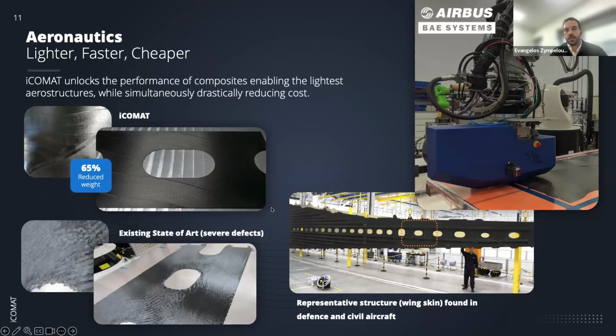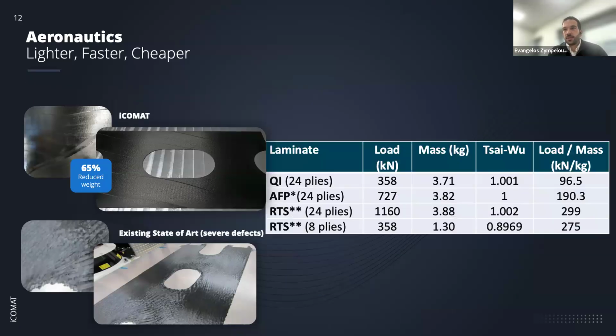So they liked it so much, they said, okay, can we try to replicate that design with existing fiber placement systems that we use today? And the result is what you see on the bottom left-hand side of the slide. It's full of localized buckling and wrinkling, which are localized defects that not only reduce performance, but they also make it almost impossible to certify. And these are some of the results. So with our technology, which is RTS, which stands for rapid tow shearing, we're able to achieve 3 times the load to mass ratio compared to the QI laminate that's flying today.